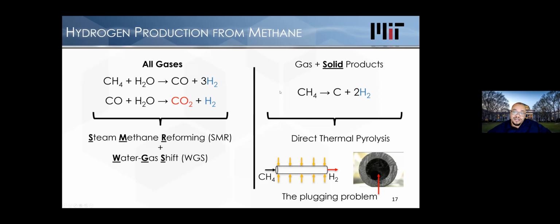What we want to do instead is take methane, heat it up to about 1400 degrees C in the absence of oxygen. We're not combusting it. We're heating it up and pyrolyzing it. At 1400 C, this molecule is no longer thermodynamically stable, and it breaks apart and the hydrogen gets liberated as gas, and then you end up with solid carbon, all right?